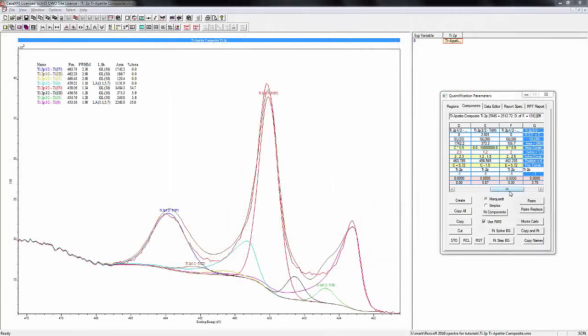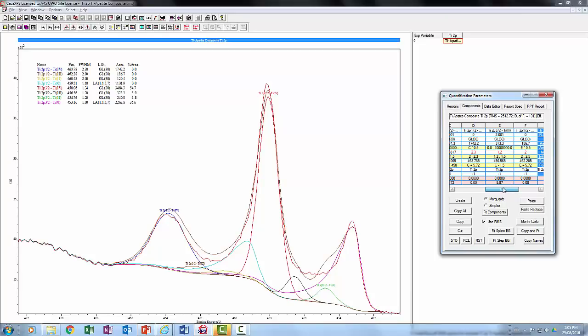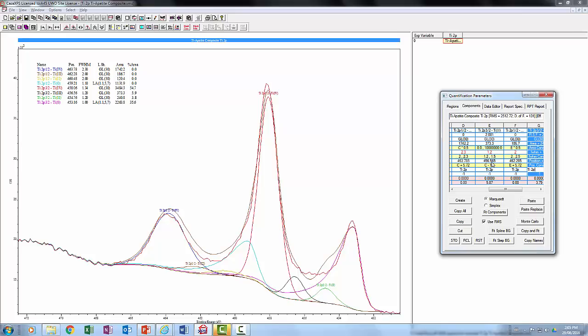I've gone in and done all the constraints needed for the titanium 2+ and titanium 3+ species. The one thing I'll mention is that we actually allow for a little broader peaks for the titanium 3+. There's not really good literature spectra out there for these, and they're supposed to have some multiplet splitting associated with them that may not be resolved, but it may just result in some broadening of those peaks. So we allow for that broadening within these.